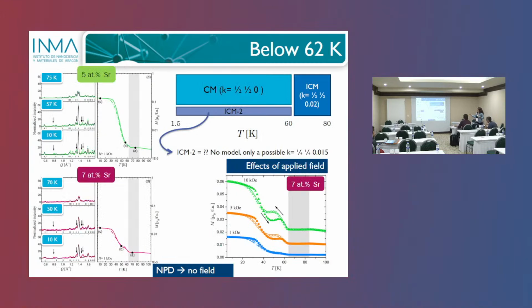When you increase strontium content to 5 and 7, what you get is that you keep this commensurate 1/2, 1/2, 0 phase all the way down to 1.5 Kelvin, and you also keep these additional small peaks for which we can't find a model. We can't find a model for these peaks because they are very tiny, and we are immersed in a very complex phase already, so it is not reasonable to obtain a complete model for these peaks. But they are there indeed, and they are there in the 3 samples, so something is definitely going on. And we think that this is strongly related to what happens when you increase magnetic field. In the magnetization, the increase of the applied magnetic field has a strong effect also in the hysteresis and the coexistence of these phases that we are observing.